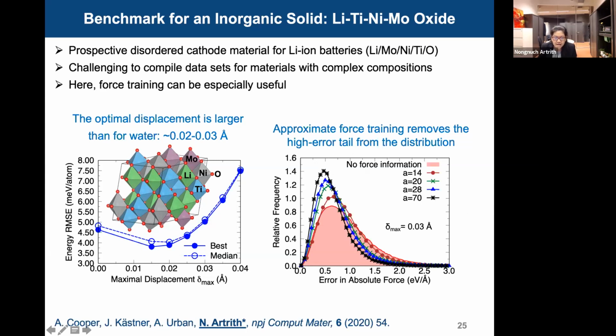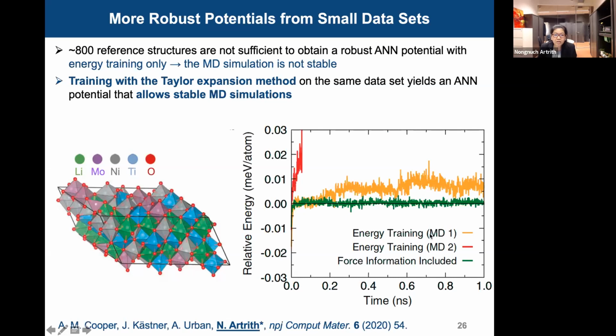After constructing an example as a benchmark of neural potentials, we use only 800 reference DFT structures that we developed, and then we include force information by Taylor expansions in the training set. And you see that neural potentials using the information from Taylor expansions improve the stability of long MD simulations, even to 1 nanosecond. But then look back: only using 800 structures with only DFT energies in the training set, and then using it in the applications and running MD, you can see it does not really equilibrate and also fluctuates very much.